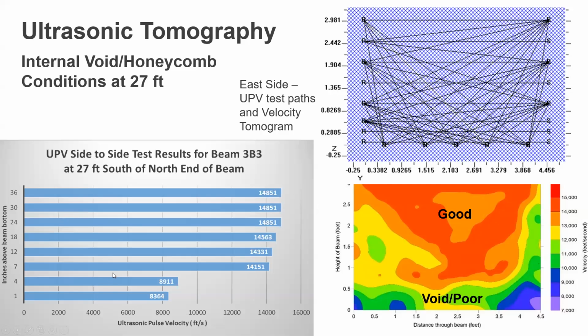The next one at 27 feet, similar coverage with semi-direct straight across tests of the beam. This one's more variable. The bottom two measurements at 1 inch and 4 inch, even though it looked less severe void and honeycomb, there is more present because you've got slow velocities on just straight across average of 8,300 to 8,900 feet per second. But at 7 inches up, it jumps up to being more reasonable, 14,000 and higher. The tomogram itself in this velocity scales goes from 7,000 to 15,000 plus feet per second. Again, shows that there are bottom areas that were more severe, and you can see this one going up here, undoubtedly affected this 8,900 feet per second velocity more.